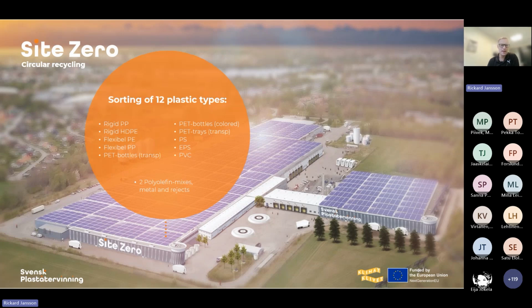You can see here that we even say that we separate PVC, and that is not mainly due to that we want to recycle the material, but we need to get it out of any other fraction, even out of the sorting reject, because PVC contains a lot of chlorine, and if we would leave it in our sorting reject, the chlorine content would produce a lot of hydrochloric acid in the incinerator, which would corrode the incinerator and chimney of the incinerator. So we need to separate PVC, and this PVC fraction that we get out, we will actually put on landfill. So we definitely don't want to see PVC, but it is still the case that in the waste that we receive, we have approximately 1% of PVC in the incoming waste.